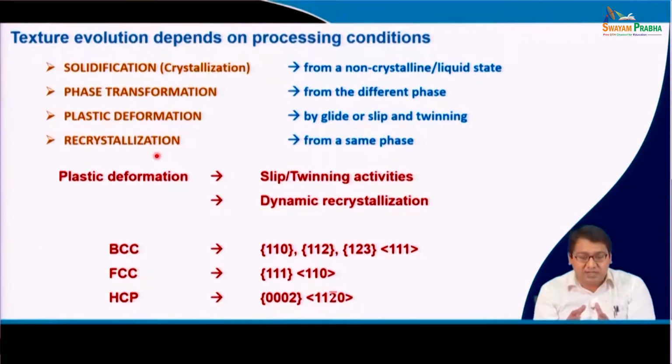recrystallization takes place. And all this process of reducing the stored energy and formation of new grains will lead to a change in the previous texture formed by the plastic deformation process, and therefore, texture evolution cannot be avoided by any kind of processing in the material.